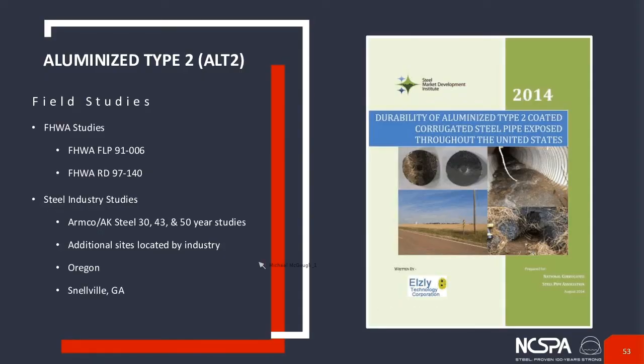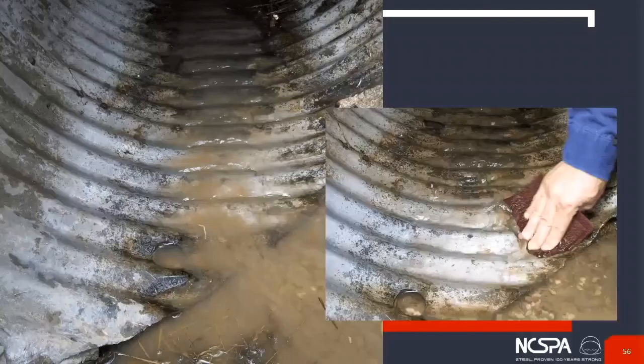That was the original evaluation protocol, is that core samples were drilled out of the invert of the pipe. Let's see this a little better in this next slide. So you can see this hole here that was drilled out. That was probably from the 43-year-old study, because this was the one that we did back at 50. So we're not doing this anymore, I think, is the long and the short of it. With the advent of ultrasonic thickness gauges and dry film thickness gauges, we don't need to do destructive testing on the pipe. We can go in, and there are even waterproof probes that you can stick in, and you can find what the coating thickness is on each of these without taking the coupon. And our most recent study drew the parallels to show that.